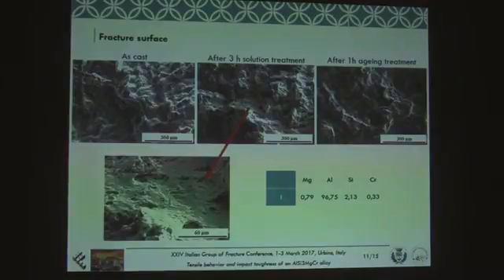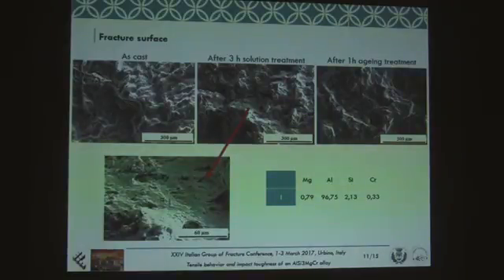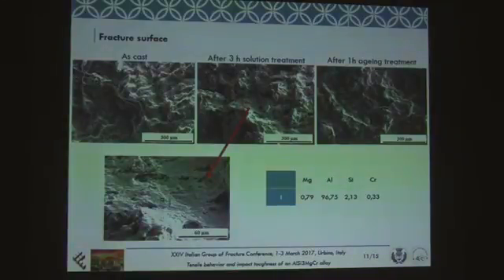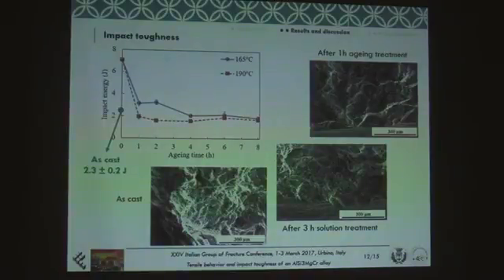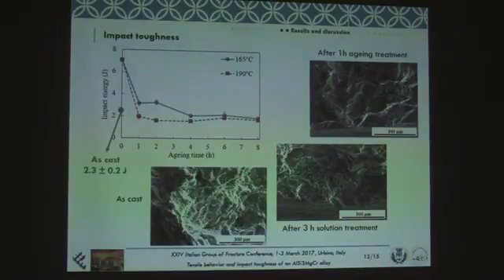Here are the fracture surfaces in different heat treatment conditions. The fracture is mainly ductile, and in some cases it shows a dimple morphology. Even if sometimes we also have a mixed fracture, we also see some regions with the aluminum matrix on the fracture surface, as shown by EDS analysis. If we consider the impact energy of the material, again we see that heat treatment at higher temperature leads to a very fast loss of impact energy, so heat treatment at lower temperature is suggested — always for short times — and again the typical fracture mode is ductile.